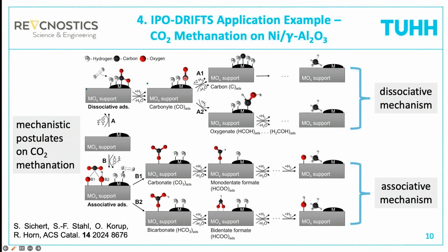And now either the carbonyl species are hydrogenated and we get some oxygenate intermediates, and then it goes through to methane, or the CO molecule dissociates further into carbon and oxygen. The oxygen leaves as water, and then the carbon is hydrogenated to give methane. And this is called the dissociative mechanism, because the CO2 molecule dissociates upon adsorption on the nickel nanoparticle.